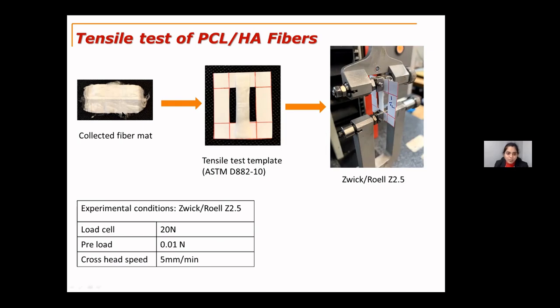This is the fibrous mat collected from the PCL hydroxyapatite fibers, and these mats were cut into samples here. The width was around 5 to 7 mm. It varied a little bit because we are cutting them manually. And the length between the grips is constant, it is 20 mm. The thickness of these fibers is measured using a micrometer, which has an accuracy of 0.001 mm. We measured the thickness at 10 different places and took the average thickness of this mat.